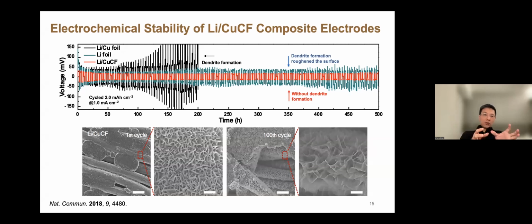But as you cycle for 100 cycles, that's somewhere around over here, we don't really see any non-uniform aggregates or big chunks of lithium metal. Instead, we see every single fiber is well and uniformly coated with a layer of lithium metal, and the entire electrode is coated with a layer of lithium metal. Here, we just use a needle to poke it through so that we can see what's happening underneath. Compared with the overpotential characteristics, it tells us that this structure helps us stabilize the lithium metal and prevent dendrite formation in most cases.